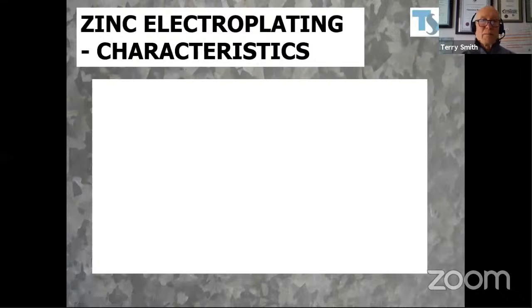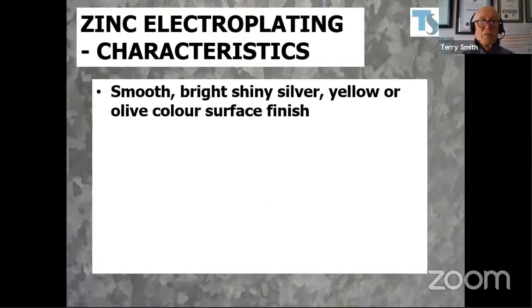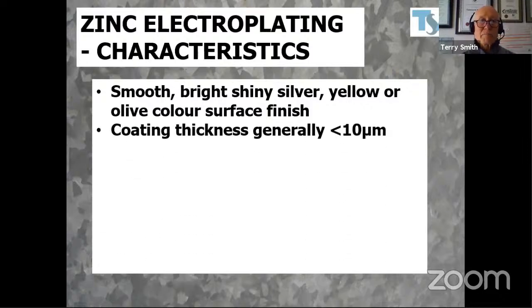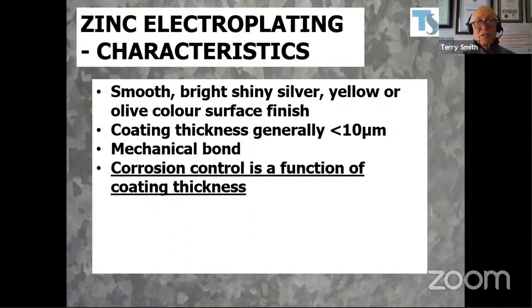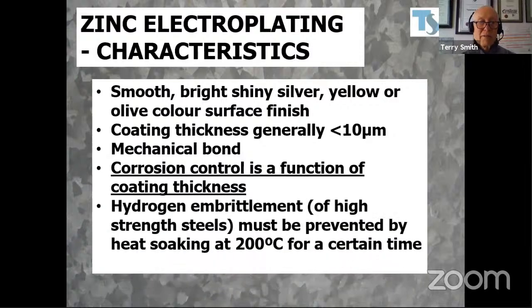Zinc electroplating characteristics: smooth, bright, shiny silver or yellow or olive in color. Each of these colors has a different corrosion protection, slightly more advantageous for the darker colors. Coating thickness is generally less than about 10 microns. It's a mechanical bond. Corrosion control of a metallic zinc coating is a function of coating thickness, so the thicker the coating, the longer it will last in any particular environment.